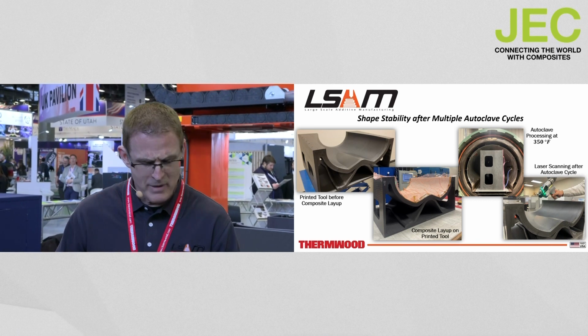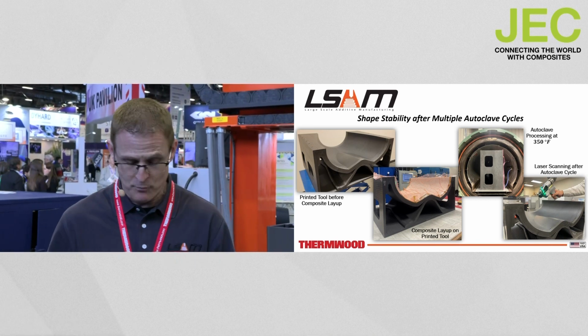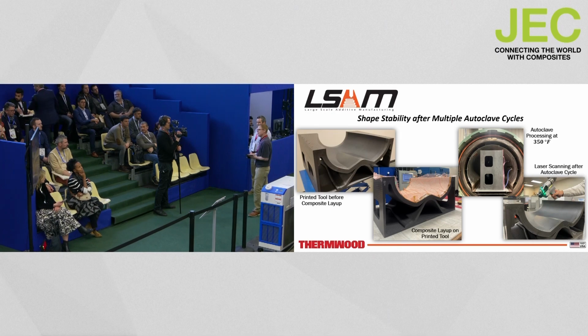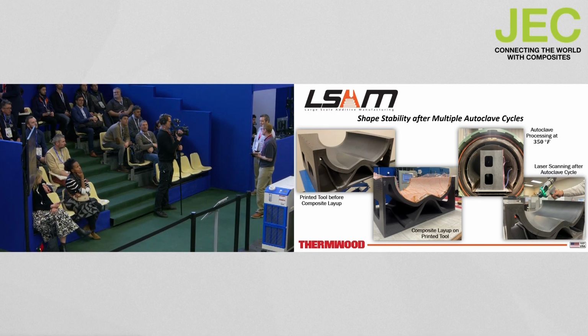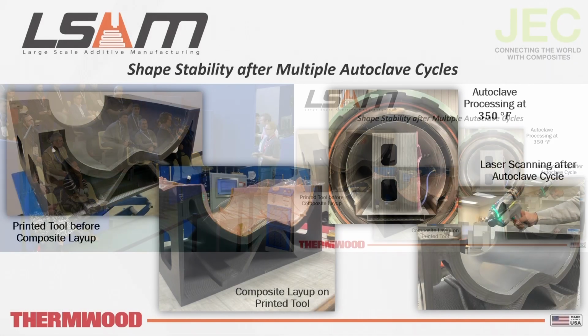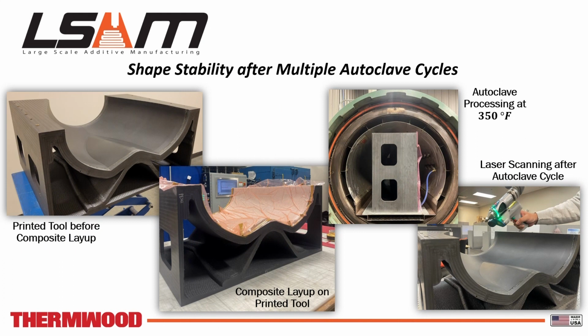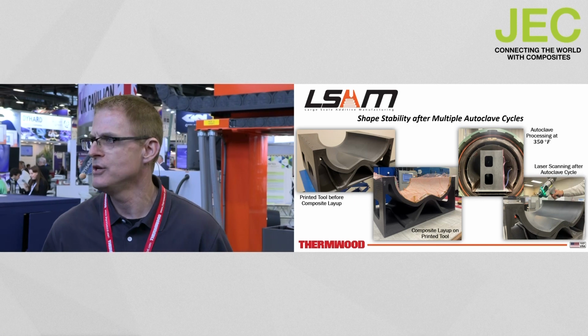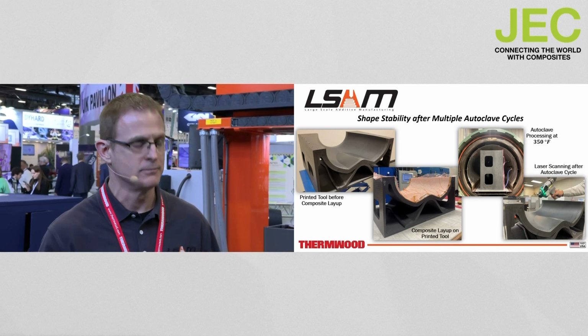I would like to also mention that the study shows that LSAM printed tools have excellent shape stability after multiple autoclave cycles, showing that longevity can be expected. So with all these factors considered and understood, we can create first-time right printed tooling that has vacuum integrity directly off the machine and produces dimensionally correct finished parts.